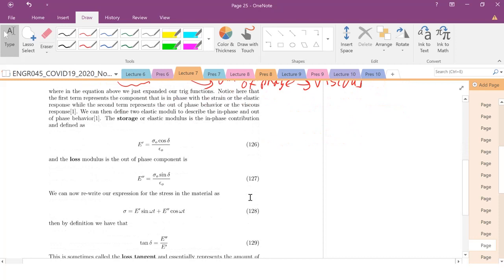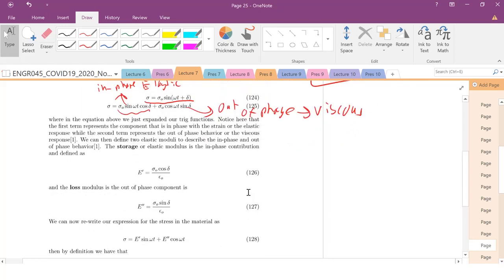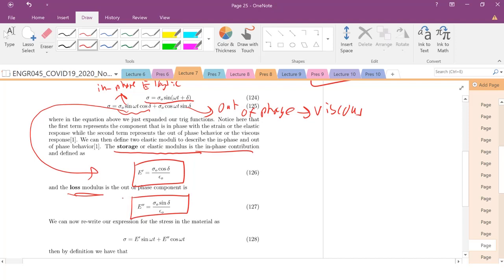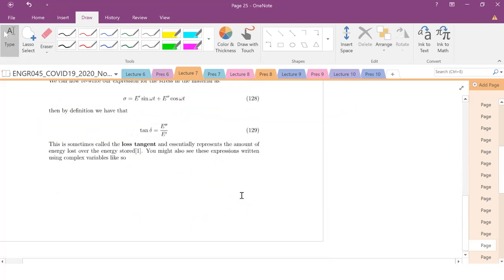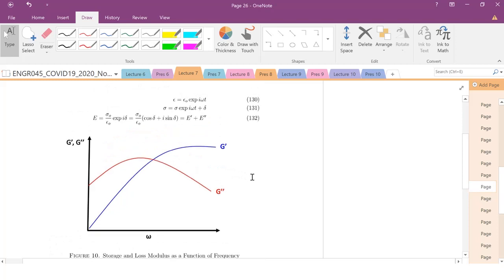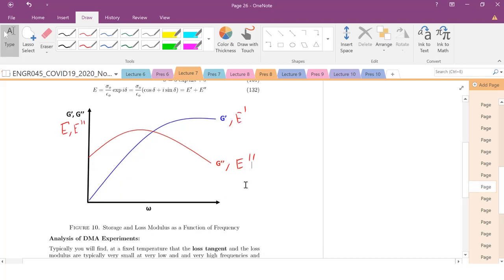You can rewrite the stress and define a storage modulus — the in-phase, elastic contribution — and a loss modulus, which is the out-of-phase viscous contribution. There's also a loss tangent. This gives you a really powerful plot of G-prime and G-double-prime, or equivalently E-prime and E-double-prime, as a function of frequency.